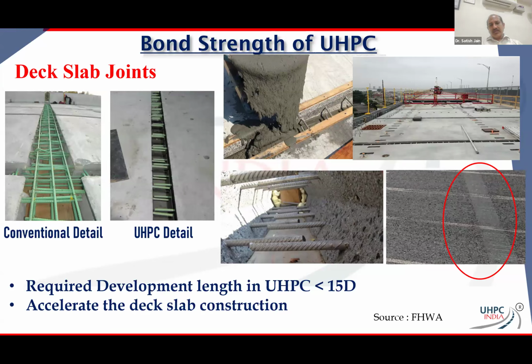Now, to tell you very simply, if you look at the rebar development length in concrete, we are typically talking in the range of 35 times diameter to about 50 times the diameter, right? But when you look at UHPC, the rebar development lengths are just about 15 times the diameter. In fact, it is the Swiss code that says about 15 times the diameter. If you look at the latest AASHTO recommendations, they pretty much say 10 times the diameter. But you can imagine that the stitches and the joints get very, very thin, and they are quite robust. In general, when we say joints, we say they are the weakest links in any kind of connections, or any connections are the weakest links.